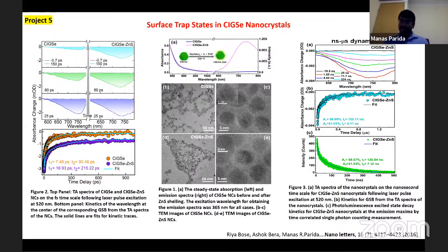And here I am showing the transient absorption spectra. You can see this is for only CIGS, and here with the shelling, and with time interval you can see how it changes. For only CIGS, it is a faster recovery rate, but in presence of zinc selenide, it takes a longer time to recover. As I mentioned earlier, we need very efficient electron transfer.